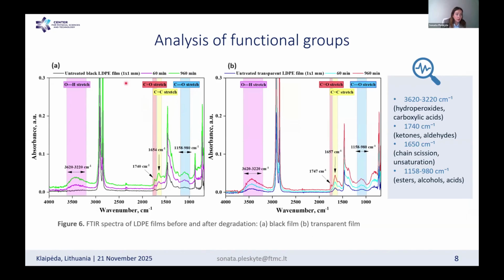So you can see over in part A, you can see the black LDPE films, and in part B, you can see transparent films. So I will start with the black color, and I'm not going to discuss each of the peaks that you can see in the graph, but I want to draw your attention that for black LDPE films, after 1 hour of UV radiation in the presence of catalyst, we already can see the formation of a new peak at 1,740 inverse centimeters, which corresponds to the carbonyl group.